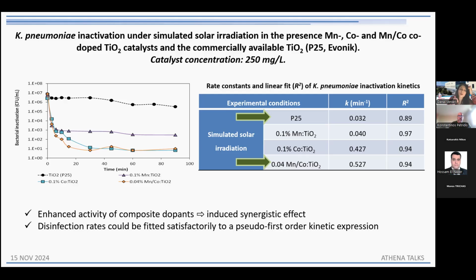We achieved an almost 7 orders of magnitude reduction of our bacteria. But again, take a look at the tailing off of the curve. We're talking about an extremely resistant bacterial species. So there is this tailing off curve. There are remaining cells after disinfection. But of course, yes, the binary doped catalysts, manganese and cobalt, seem to be quite effective, at least compared to the commercial P25. P25, I'm just reminding you, is the pure titanium dioxide without any dopant.